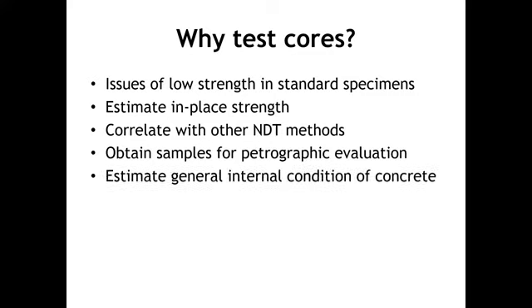It is always better, before you test these cores, to have the number of data available with you so that you can correlate it with the other values, and then do the capping. Normally we do sulfur capping so that you can avoid the curing time, and you can do the testing at the earliest. So this is how it is done. Once it has been done, you correlate with that, and then you give your cube compressive strength.